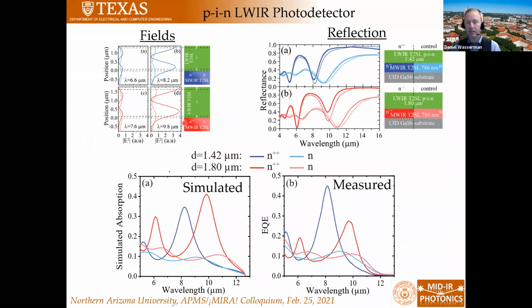So we did exactly this, and you can model the fields. You'll see that in the structures with the doped virtual substrate, you get a very strong field enhancement. And you can see these characteristic dips in reflection associated with the cavity modes. So this is experimental and simulated data. If we look at our simulated and our measured response, you see a really nice improvement in external quantum efficiency. The solid lines here are two different detectors with different thicknesses, so we're essentially tuning the cavity thickness, that interference resonance. And then the matching colors are with a lightly doped substrate, so it doesn't have the doped substrate. So you see a factor of 4 improvement in your quantum efficiency for these devices.